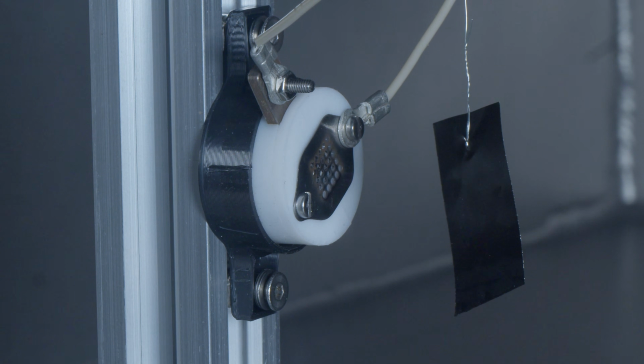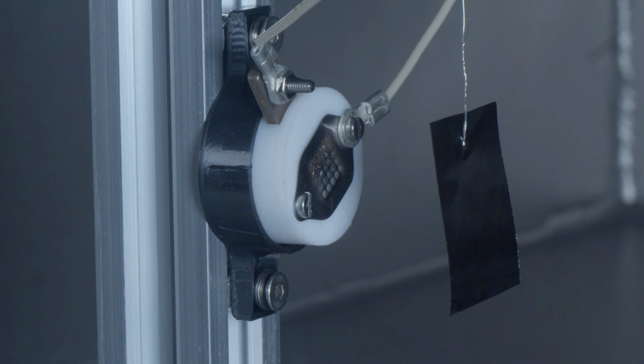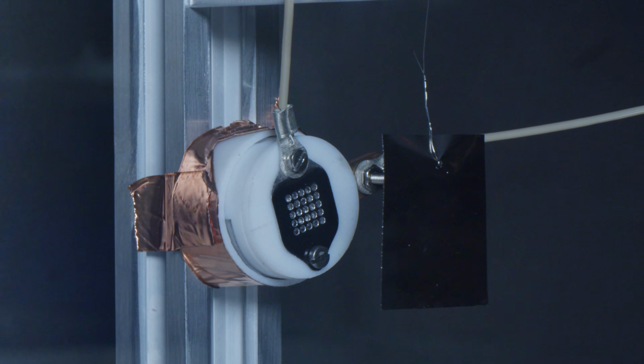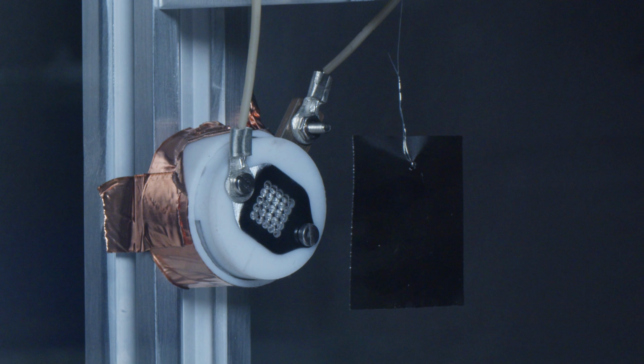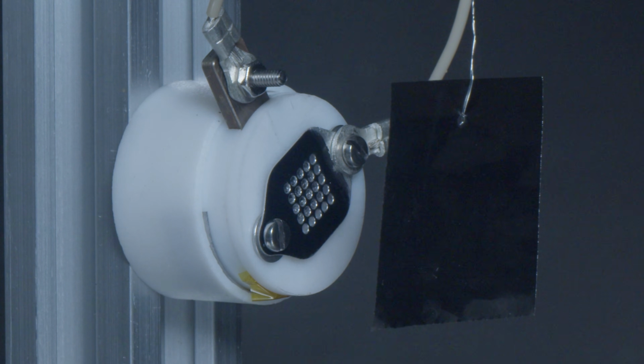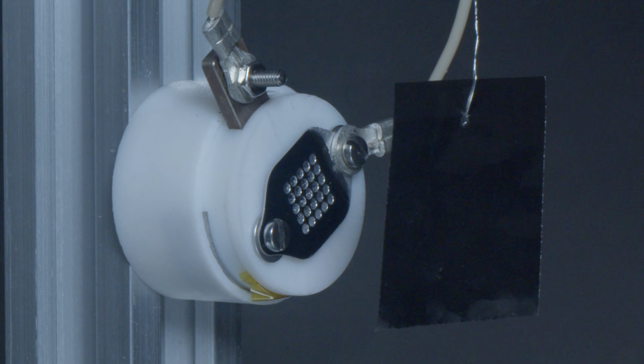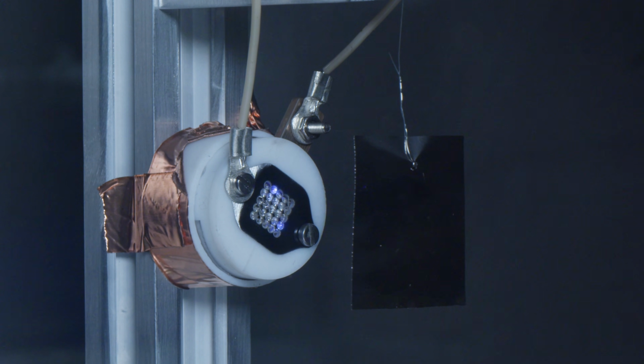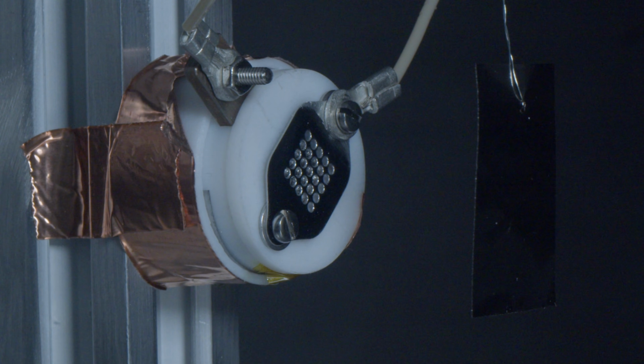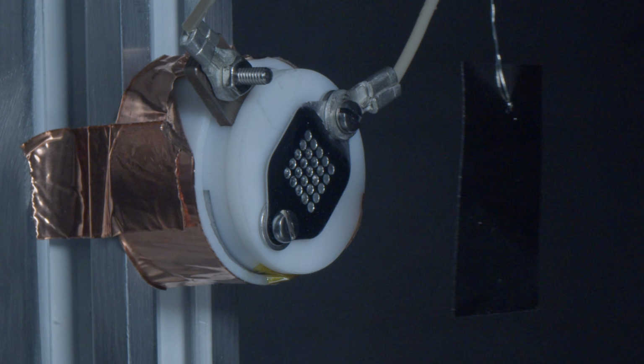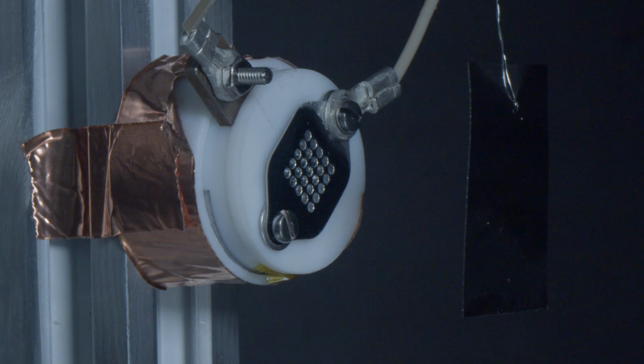Since the spikes are all in the same cavity, I think even the smallest arc or emission would generate enough plasma to lower the conductance inside the chamber. And then that would trigger more spikes to emit, and the effect would cascade across the whole array. If the spikes were loaded with too much gallium, sometimes a blob would fly off and short out the array. I tried a variety of hole diameters and spacings and just could never get a stable configuration to work.